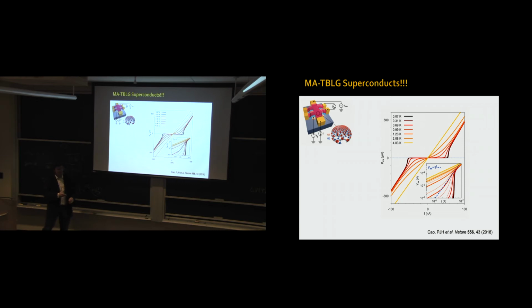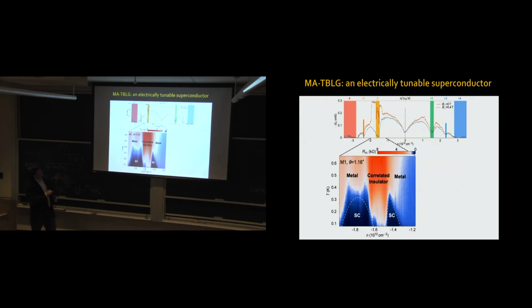Now remember, we have this gate voltage, this knob, with which you can vary the density of carriers in our system. So the thing that we can do, and that has attracted perhaps the most attention, is the following. We can zoom in on this region, and now we can measure the resistance as a function of temperature and density. We have this region around 2 electrons, 2 holes per unit cell, where we have a correlated insulating behavior. We add a few extra holes, and we have a superconducting dome.